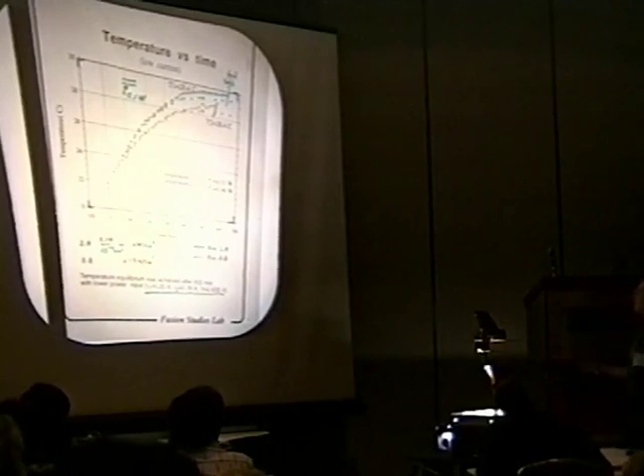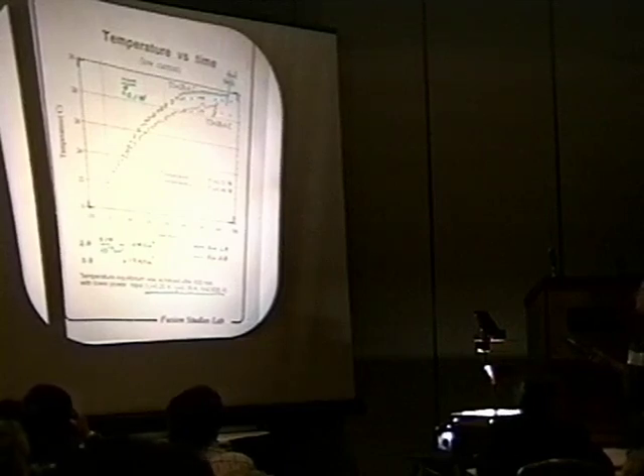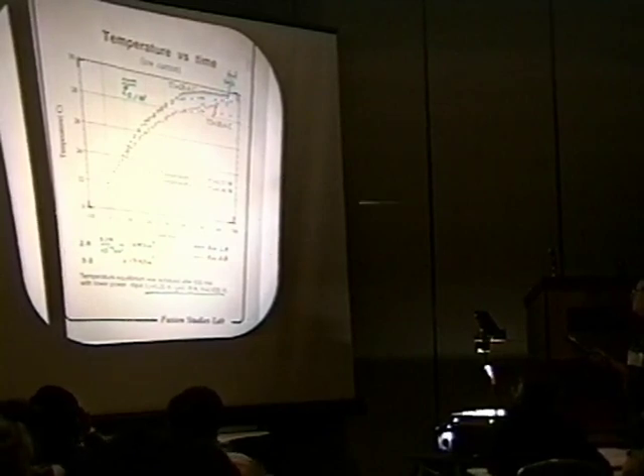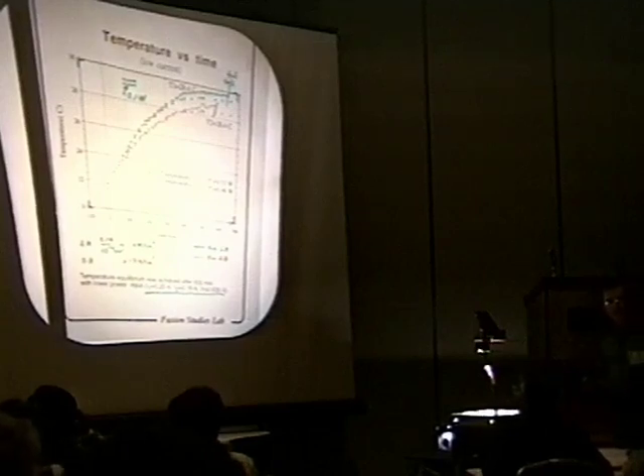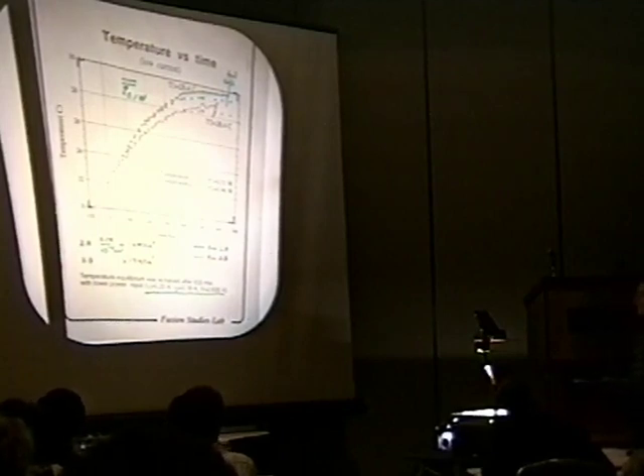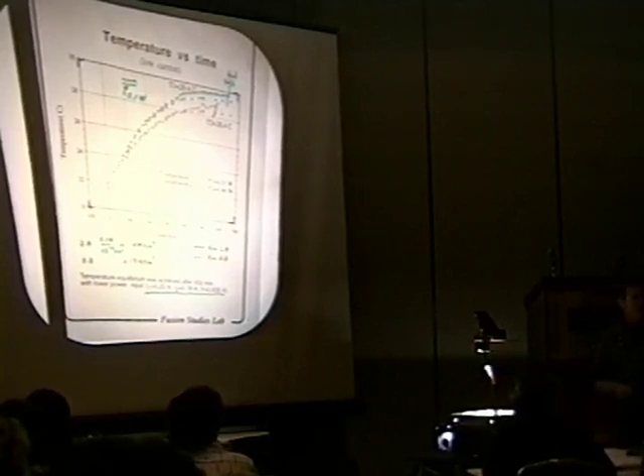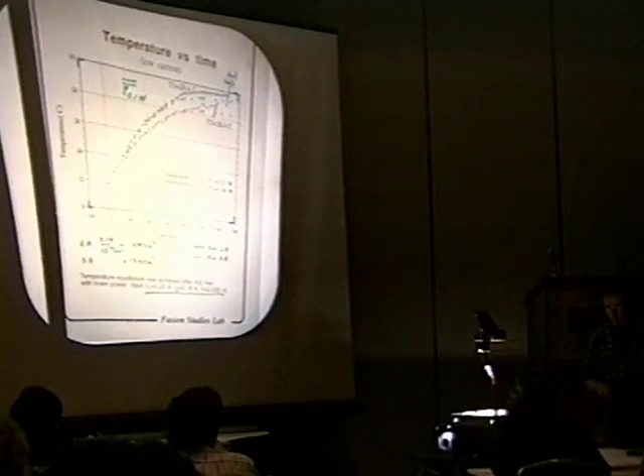And this happens at different times depending somewhat upon the goodness of the bonding we would achieve with the foils. Now, while the excess temperature rise that appears to occur with the foils is on the order of 1/10 of a watt or so, if you calculate the power density that corresponds to in the foils themselves, it is exceedingly high. With these thin foils, it's something like a kilowatt per cubic centimeter. And so I guess the destruction is not unexpected because with that temperature and different coefficients of expansion, one might expect to have problems of bonding with this type of arrangement.